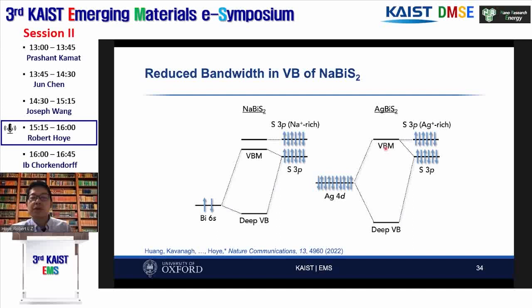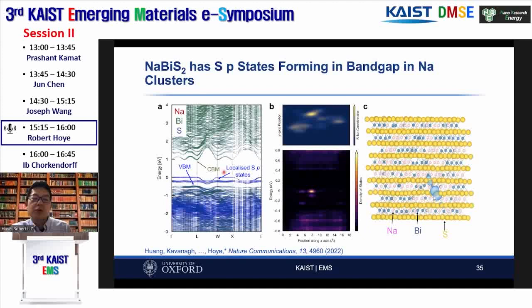Now, if you look at this E versus k diagram, you'll notice something quite interesting. You notice that we have these states forming within the valence band itself. And we found that these states occur where you have a high coordination of sodiums around the sulfurs. If you remember, I call this compound cation disordered, which means sodium and bismuth both occupy the same lattice site, but the distribution of these two cations is not the same, and that's because it's driven by kinetics.